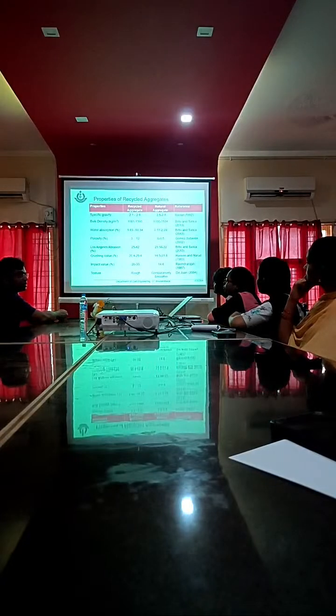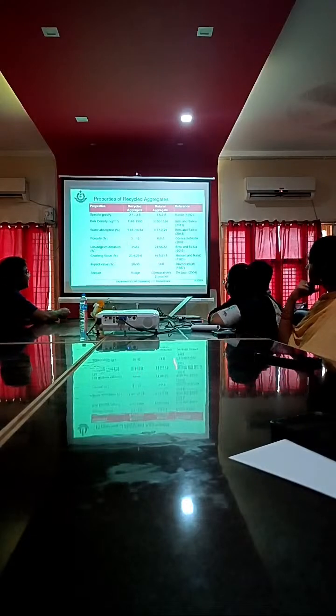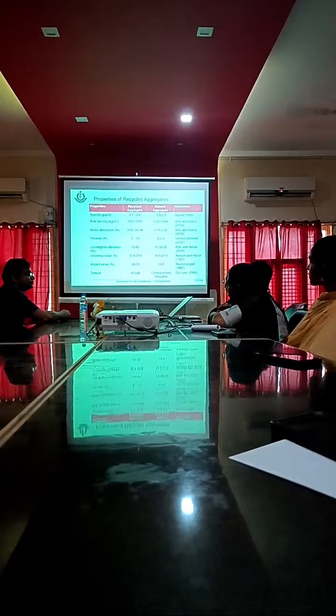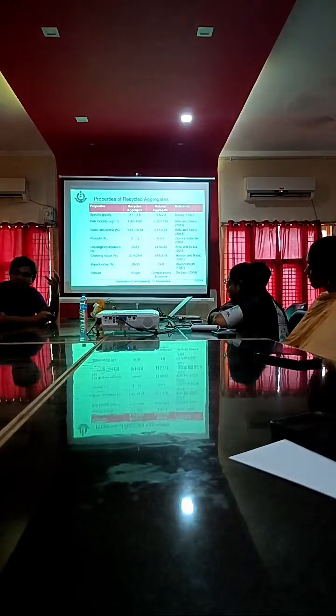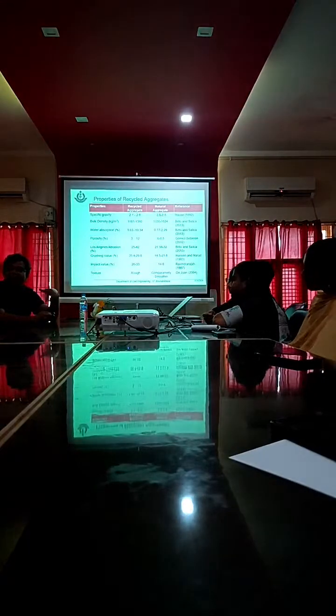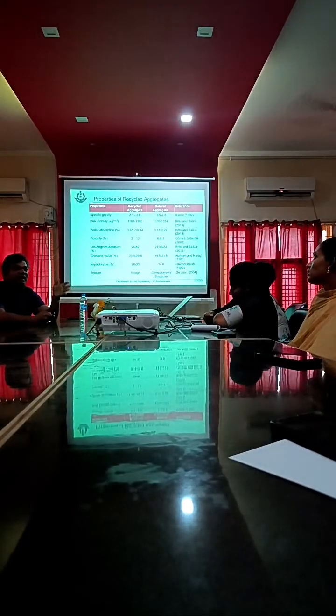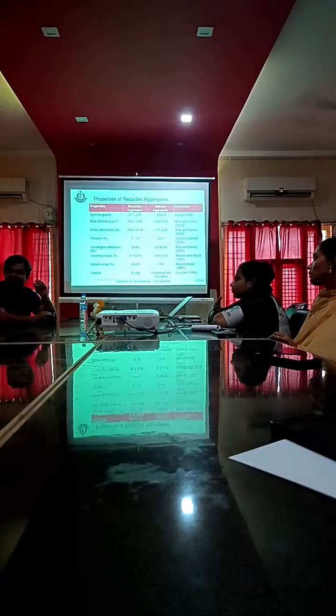And the other values you have to determine. For structural concrete, you have to determine all these properties: the abrasion value, crushing value, impact value. If these values are falling within the limits of a regular conventional aggregate, what will you do? Replace this. Exactly. If the properties of the aggregate are nearly at par with the regular conventional aggregate, you can go for 100% replacement. Remove the conventional aggregates completely and go for 100% replacement. If the values are inferior to the regular conventional aggregates, you cannot go for 100% replacement. Maybe you may go for 40% or 50%. That R&D you have to do before arriving at the optimum result.